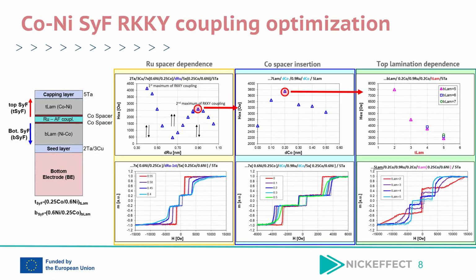The optimization of RKKY coupling in the cobalt-nickel synthetic ferrimagnet system separated by a non-magnetic ruthenium spacer was performed in 3 stages. In the first step, the ruthenium spacer thickness was optimized. As shown in the left column, the effective coupling field, Hx, exhibits an oscillatory dependence on the ruthenium thickness. The maximum coupling strength, corresponding to the second RKKY maximum, was obtained for the ruthenium thickness of approximately 0.9 nanometer. The second maximum was selected due to the wider thickness tolerance window compared to the first coupling maximum.